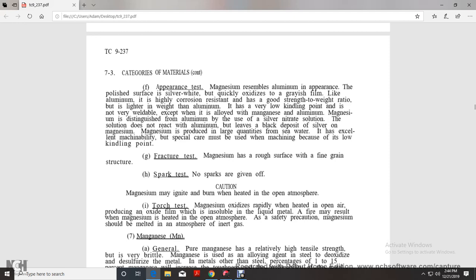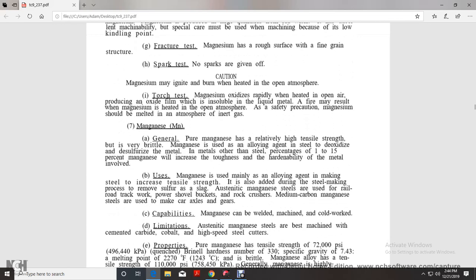Fracture test: magnesium has a rough surface of fine grain. Spark test: no sparks are given off. Caution: magnesium may ignite and burn when heated in an open atmosphere. Torch test: magnesium oxidizes rapidly when heated in open air, producing an oxide film which is insoluble in the liquid metal, and fire may result when magnesium is heated in an open atmosphere. As a safety precaution, magnesium should be melted in an atmosphere of inert gas.